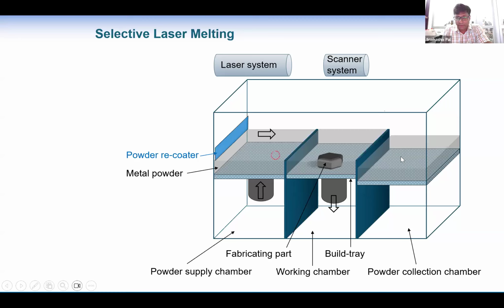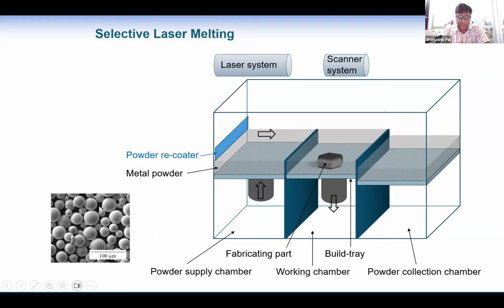In the beginning, there is a lot of metal powder kept here, which can be 20 micron to 100 micron, but more or less for titanium we use 20 micron to 50 micron particle size. For the layer thickness, we use 25 micron to 50 micron.